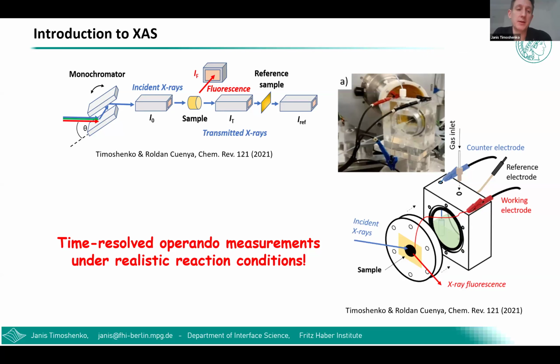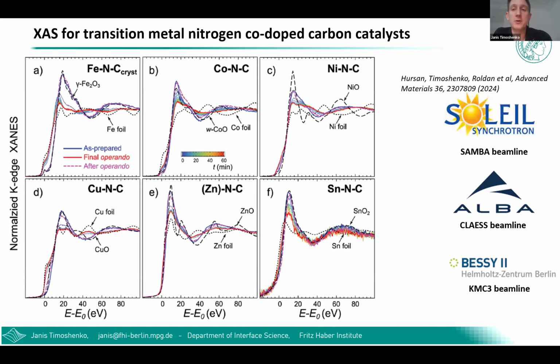Coming back to these transition metal nitrogen co-doped carbon catalysts, we looked at different ones using the X-ray absorption technique during several of our beam times in France, in Spain, and also here in Berlin. All of these catalysts respond quite significantly to the applied potential. Just by looking by eye, without any analysis, you can see that the X-ray absorption spectra for each of these catalysts change a lot when we apply the potential, so there are really significant structural changes. For different transition metals, these changes are somewhat different, and all of them are interesting and probably deserve separate discussion and presentation. But today I will focus on these copper and nitrogen doped carbon catalysts, which are quite different from the rest of this series of catalysts and have very intriguing and interesting properties.